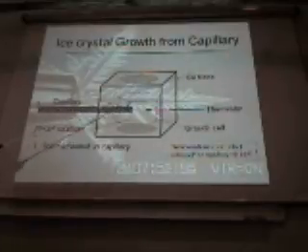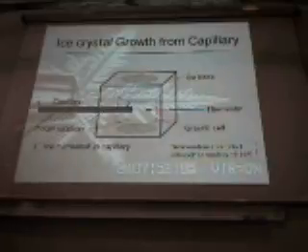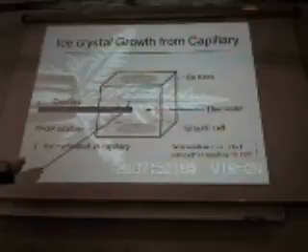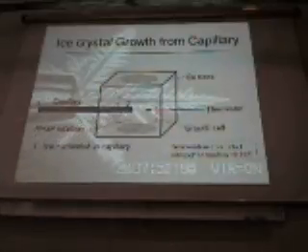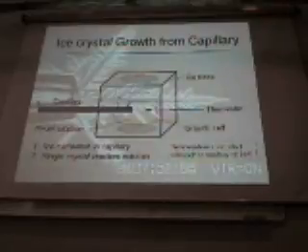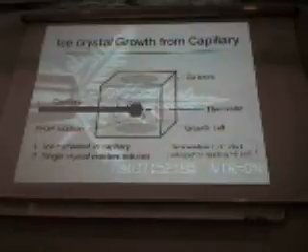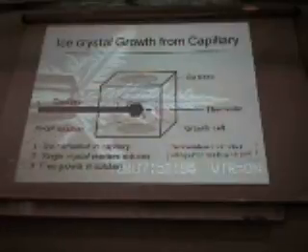This one grows along the capillary, and a growth competition can occur in the capillary, and finally only one crystal survives here. Then that crystal starts to grow like this. So we can obtain only one single crystal in the growth cell. Okay, so this is a way to observe the free growth in solution.